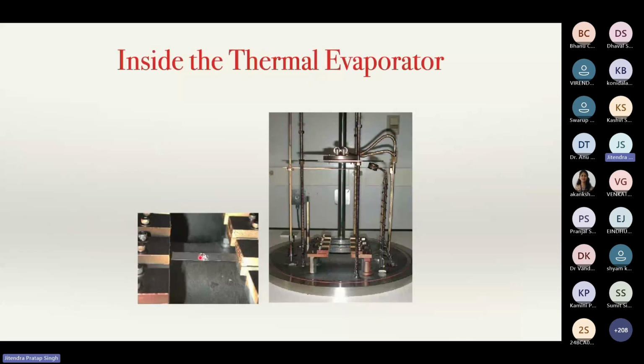I can show you the picture here. This is one of the evaporators which we have in our clean room. You can see multiple crucibles here, and there is a shutter which you put in place when you don't want material to get deposited. This is my substrate, which is cooled by water, and there is a thin film measurement setup called a quartz crystal, by which we measure the thickness of the film. You heat the material, it gets evaporated and deposited on the substrate. When you get the right thickness, you close the shutter and turn off the evaporator.